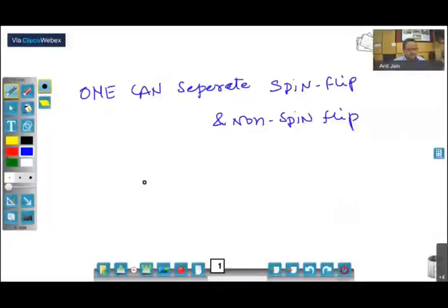It means one can separate nuclear and magnetic scattering. Suppose you polarize the sample's spin along the Z direction, you are working in the horizontal scattering geometry, and your initial neutron polarization is along the Z direction, then all your magnetic scattering will go to non-spin flip. Please keep this in mind.